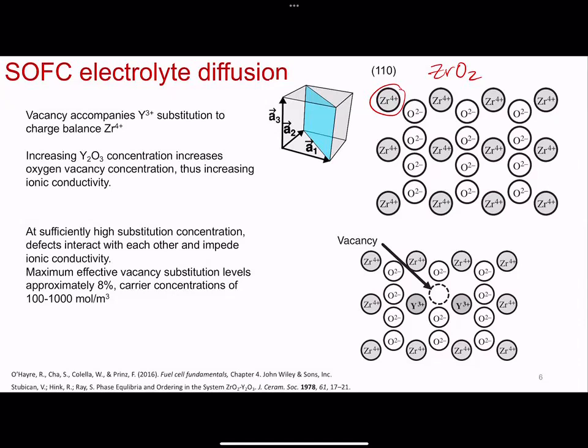You substitute with a different oxidation state, it comes with a vacancy, and now you decrease the delta G of migration, so you have to overcome the energy hump to then have the O2- pop along. Okay. So then you say, okay, why don't I just introduce a whole bunch of these vacancies to move the O2- along? You can, up until a certain point. After a certain concentration of yttria substitution, there's diminishing returns. Then you have too many vacancies, and when you have too many vacancies, they start interacting with each other, and you actually have decreased ionic conductivity.